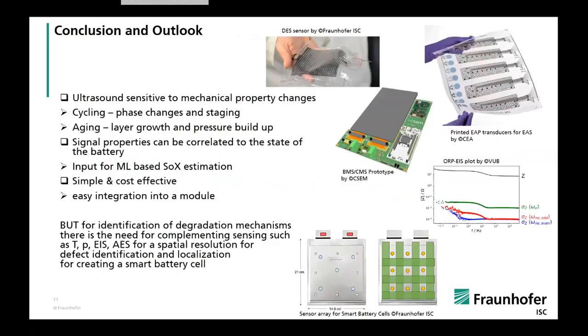So conclusion and outlook. What I tried to present here is that ultrasound is quite sensitive to the mechanical property changes in a battery cell. It helps us to analyze during cycling phase changes and staging in the graphite anode, plus aging effects like layer growth and pressure buildup due to the SEI. And these signals can actually be correlated to different state of properties of the battery cell.